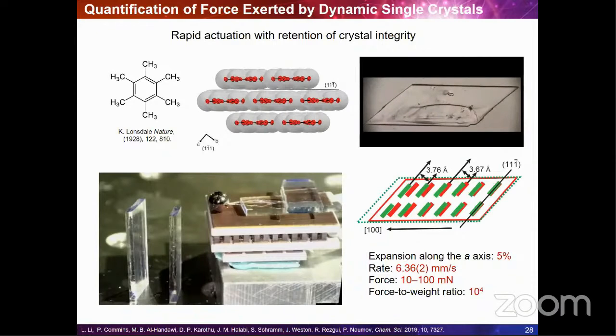So in this case, we demonstrated that the work that can be performed by this crystal is comparable to that of most actuator classes. Millimeter size crystals of this material can undergo transition between two forms by uniaxial expansion, and they exert a force of about 10 to 100 millinewtons. If you compare the force to weight ratio of the crystals, it is 10 to the 4, so 4 orders of magnitude better than some of the living creatures, for example, horses, elephants, and ants.